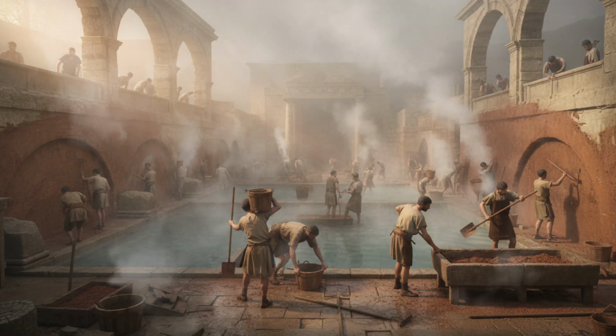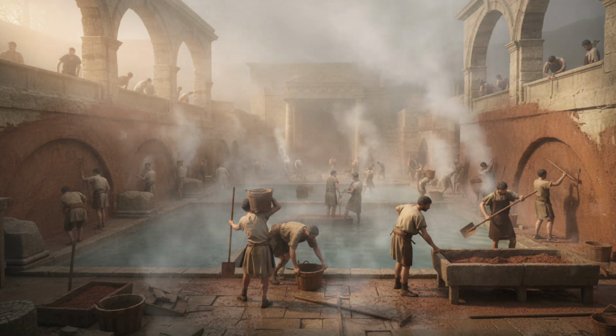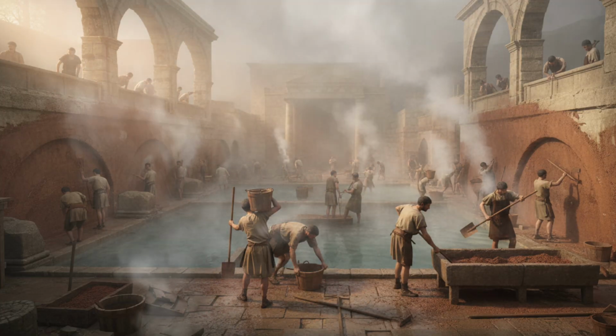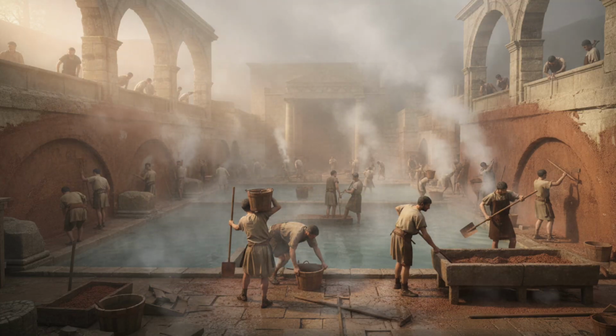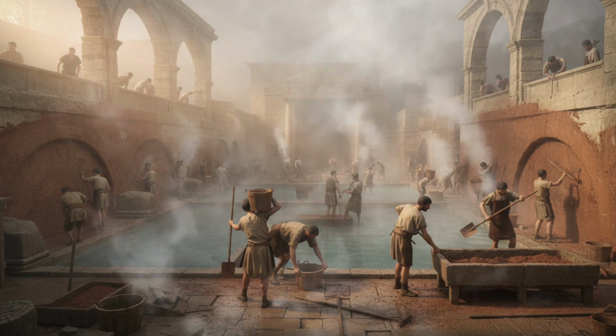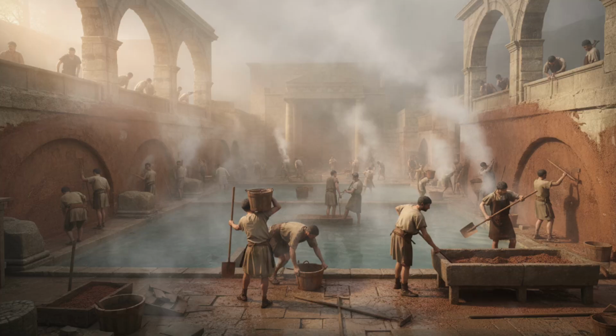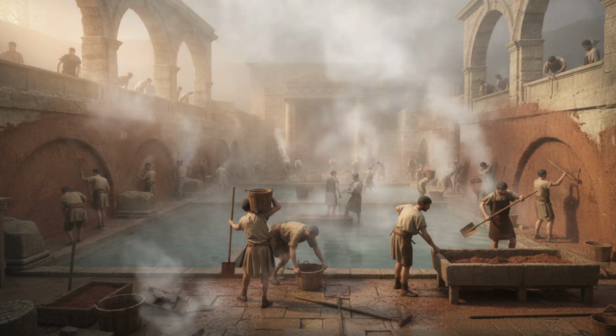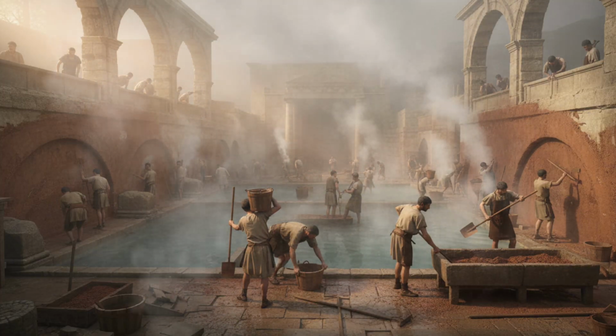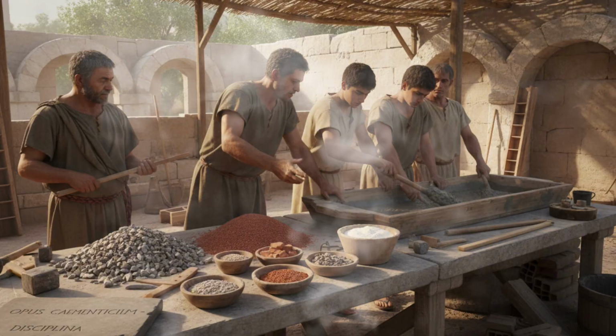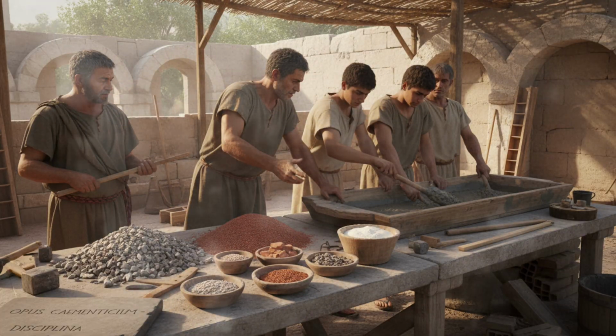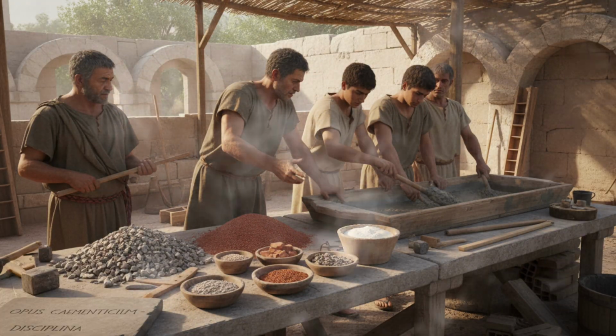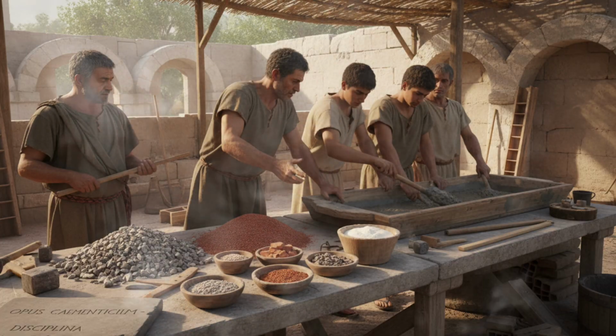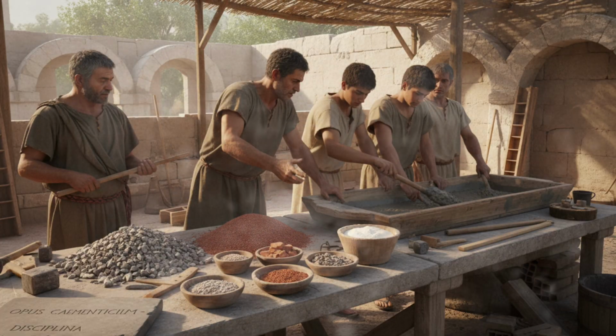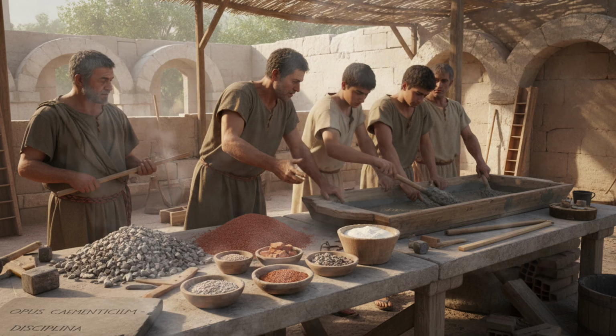These lime clasts, long thought to be defects, actually enable the concrete's self-healing properties. When cracks form in Roman concrete, they preferentially travel through these softer lime clasts rather than the harder binding matrix. This exposes unreacted lime to moisture, triggering new chemical reactions. The lime dissolves, flows into the crack, and then recrystallizes as calcium carbonate, effectively healing the damage. It's an engineered self-repair system that modern materials scientists are only now learning to replicate.